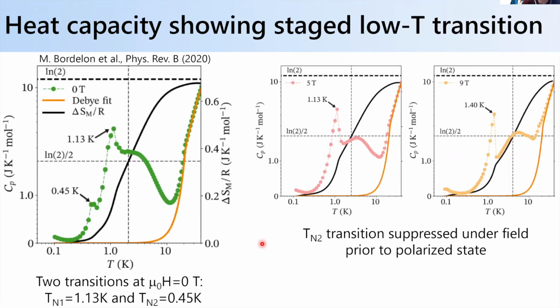And so when we look a little bit more closely, we can look at heat capacity data, right? So this is heat capacity going down to dilution refrigerator temperatures. And so again, as you cool down the system, you can see that the magnetic heat capacity comes up. You start to form some short range correlations. And then you see this sharp peak here, which roughly coincides with the peak of the AC susceptibility data. But then as you cool down, there seems to be a second transition down here at 450 millikelvin. Okay, so there's two different transitions. I call the first one TN1, the second one TN2. And then if you apply a magnetic field, more or less the second transition goes away. The first one sharpens up, and the key takeaway is that this 450 millikelvin transition is suppressed prior to reaching the polarized state of the system, which is under 10 Tesla.